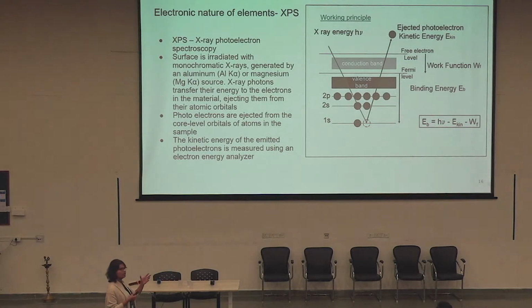Because this is something that is happening also in your EDXRF, right? When you have energy dispersive X-ray fluorescence, you are putting X-ray on the surface, there is an ejected electron, and there is secondary X-ray emission which you are measuring. How is this different from that? The difference mainly comes from what you are measuring. In the EDXRF, you are measuring the secondary X-rays that are emitted. But here, what you are really measuring is the kinetic energy of the electrons.